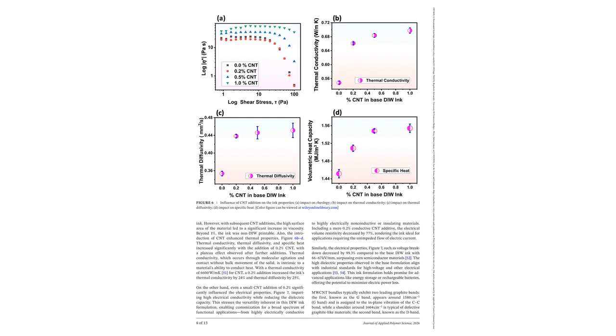As more CNTs were added, the viscosity increased as expected due to the high surface area of the nanotubes. Beyond 1% loading, the ink became too viscous to print effectively. Next, the thermal properties. The results were dramatic. Adding just 0.2% CNTs increased the ink's thermal conductivity by 24% and its thermal diffusivity by 25%.